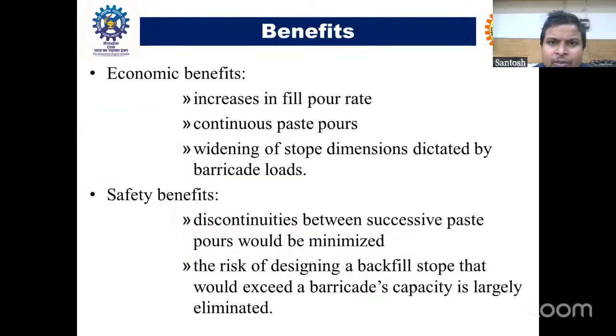What is the benefit of creating a stronger barricade? That means you can increase the fill pouring rate, and you can continuously pour paste fill or backfill. Also you can use wider stopes. If you are using wider stopes, it means you are producing more ore at a time. And definitely it will add some safety to the underground working. You can continuously fill it, and also the risk of failure of the barricade is minimized.